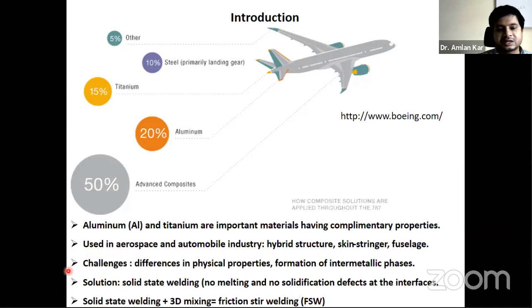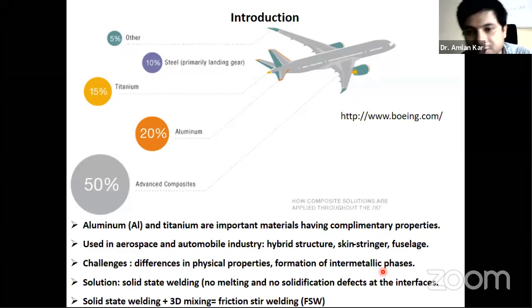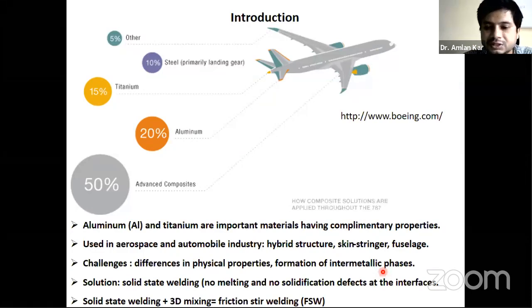But the challenge, as I have discussed here, is the difference in the physical properties and the formation of intermetallic phase. Because you know, in any welding, whenever there is an interaction between two materials at high temperature, there is a diffusion and there is a reaction. Because of that, there is a lowering of the Gibbs energy at a particular composition and a particular temperature, and that leads to the formation of intermetallic phase.